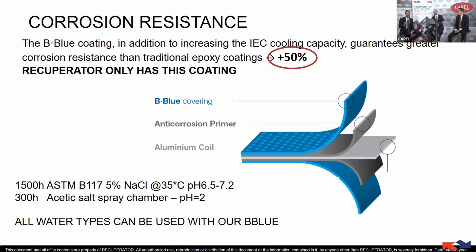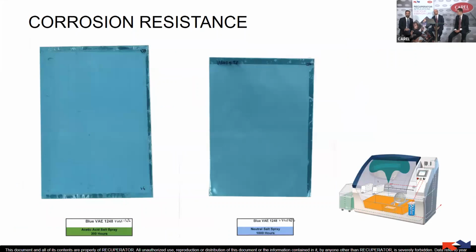This is proved by different tests we've done in salt spray chamber, reaching the value of 1,500 hours in the neutral spray chamber and 300 hours in the acetic spray chamber. This is a really impressive result. These are just the results of the test. As you can see, one edge of the sample is not covered by the tape, so the corrosion could start from that point, but it did not, thanks to the right addition of the primer with aluminum.